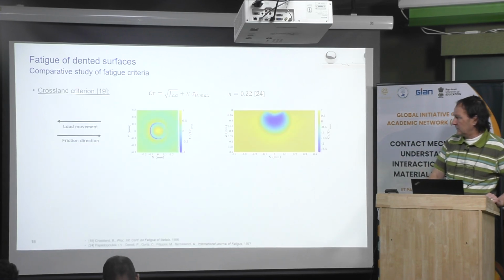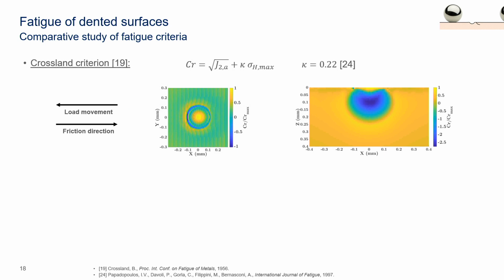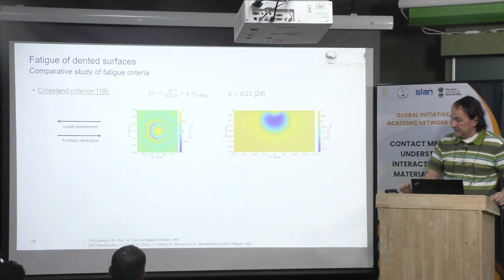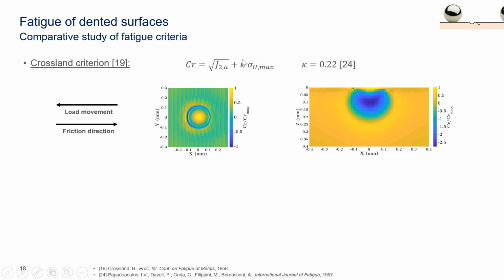I will present you some results. So, for example, this is the result for the Crossland criterion. And each time you have a parameter to give some weight to, for example, the mean stress or the shear stress. And von Mises corresponds to shear stress, in fact. Okay? Von Mises and Tresca are about the same. If you have a pure hydrostatic pressure, von Mises equals 0. Then von Mises corresponds to shear of the material, as in all other models. Now you have the constant, which is in fact one of the keys. This parameter is important because it can mask a lot of things. Then what you can see on the left is a top view, and this is a cross view. You cut the dent in two.